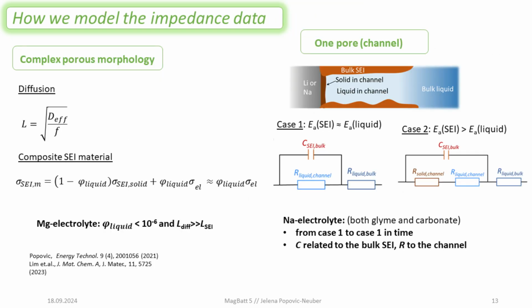So this is the reason why I have been trying to do it a little bit differently, and there are two extremes that I have been using in this case. We have porosity and we have liquid channels. We either try to fit this model as a kind of one pore, one channel, and then try to imagine that we have many of these pores and channels in such an SEI. In this case, we have seen two cases.